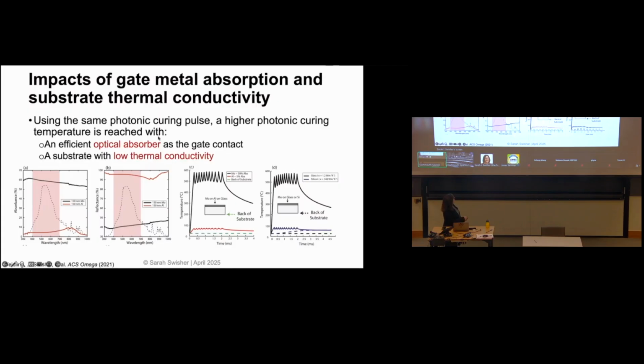So one of the things we found is that it makes a really big difference what you use for that metal. So for example, this plot right here is showing, for the same illumination, what is the temperature if we have molybdenum as that gate versus aluminum as that gate. Same amount of light, right? But what happens is the aluminum is a beautiful reflector. And so the light doesn't get absorbed, it just gets reflected off and you don't get any heating. So you have to have a really strong absorber in that gate.